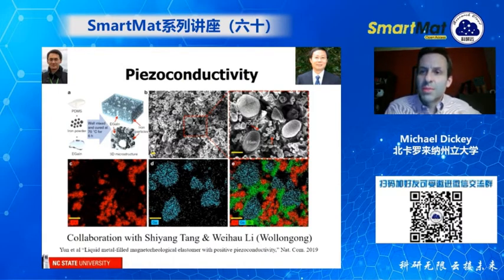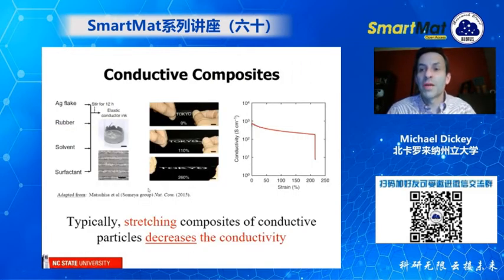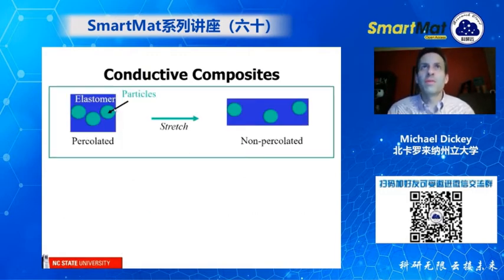Now, why is this interesting? Let me tell you what typically happens in composite materials. This is some really nice work from the Someya group in Japan, where they mixed silver flakes with rubber. And they were able to make a stretchable conductor that worked really well. But as you might guess, if you start stretching these composite materials, the conductivity eventually goes down and then eventually fails. So typically when you stretch a composite, the resistance will increase or the conductivity will decrease. So why is that? Well, if you have a composite with particles and you stretch them, you typically pull them further apart, which means they're going to be more resistive.